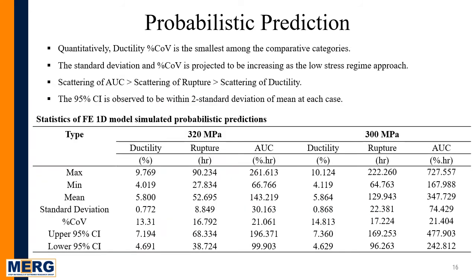The quantitative analysis of these probabilistic predictions is done across three categories, that is ductility, rupture, and the area under the creep curves. The ductility percent coefficient of variation seems to be the smallest among the comparable categories, and the standard deviation and the coefficient of variation are projected to be increasing at the lowest stress regime. And the scattering of the area under the creep curve seems to be the highest, while on the other end of the spectrum, the scattering of the ductility seems to be the smallest. And the 95% confidence interval is observed to be within 2 standard deviations of the mean in each case.